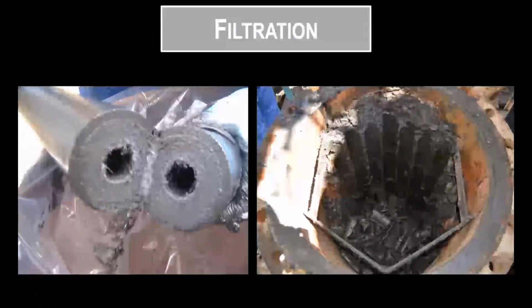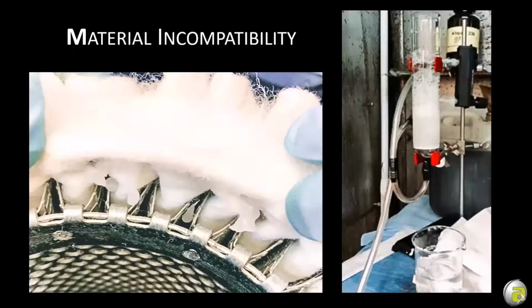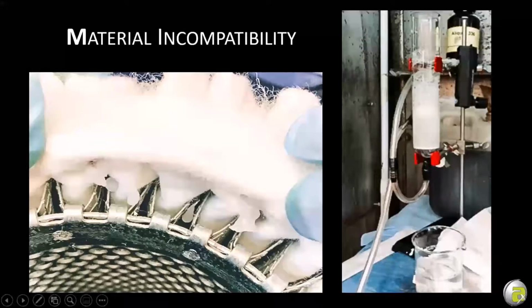Filters are made to be changed on DP. Also, sometimes your filter material is incompatible. This is a fiber that was used in an amine filter. We took a piece of the fiber, put it in amine solution, ran a foam test, and you can see there's a very stable foam head. So whenever they changed the filters, the solution foamed.